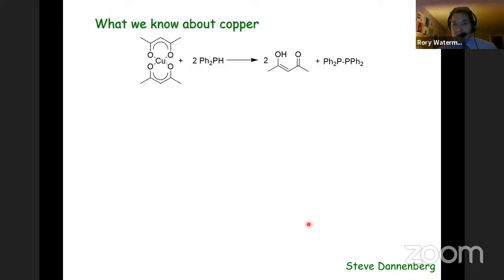What do we know about this? So we're midstream in mechanistic studies to understand better the copper and then how to optimize that particular catalyst. And so what we do know is that the copper reacts with diphenylphosphine under reaction conditions to simply protonate off the ACAC ligand, which is telling us something important that's unique to certain kinds of reactions with copper. The really important observation is the tetraphenyl diphosphine. And so this coupled product is telling us that actually we're going from copper 2 to copper 1.